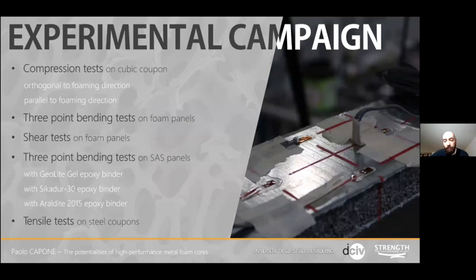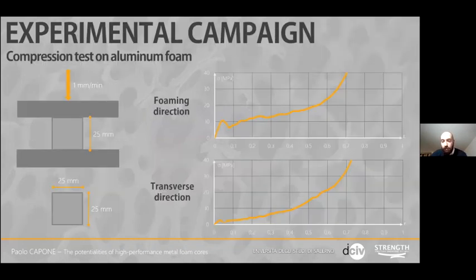To fully understand the capabilities of this material, an experimental campaign on metal foam and SAS panels has been set up. In the first step, tests have been performed only on the aluminum foam in parallel and transverse compression. The material has two different values of resistance and elastic modulus in the two main directions. It is higher in the foaming direction than in the transverse direction due to the lamination process that deforms the voids of the external layers of the aluminum foam panel. The most interesting thing of these tests is the absence of a degradation phase for the material in compression. In fact, the foam achieves a plastic strain of about 0.9 without any loss of resistance.